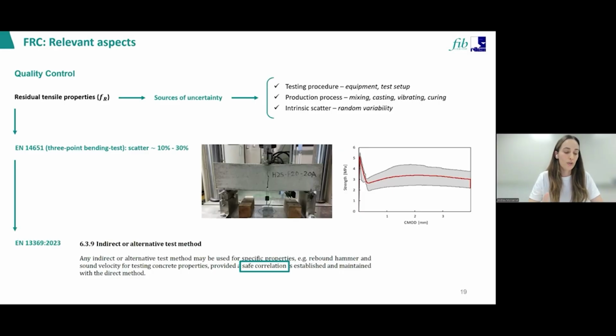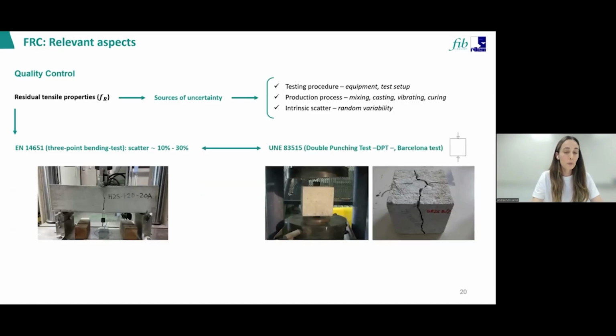So in this regard, although Eurocode 2 does not explicitly refer to alternative testing methods, this procedure may be used for quality control purposes, provided that a statistically robust correlation is established between the 3-point bending test and the alternative test method. One example of this alternative test method could be the double punching test, also known as the Barcelona test. Compared to the conventional 3-point bending test, this methodology presents several practical advantages because we use smaller specimens, simpler experimental setups, and easier execution under production conditions. But the most important one is that the larger fracture surface involved in this type of test reduces part of the scatter associated with the characterization of the residual properties.